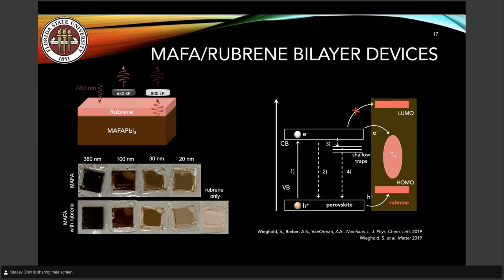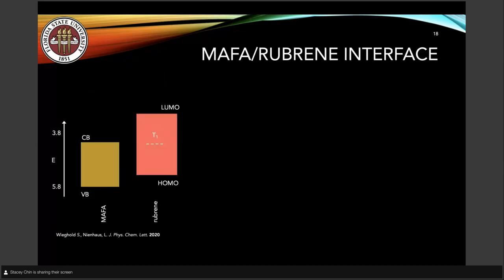And so the idea here is that you excite the perovskite, so you create free carriers, you have a hole in the valence band and electrons in the conduction band, and you do hole transfer and electron transfer to the triplet state of rubrene. Next slide. We spent some time looking at this interface because it seemed to be not quite as trivial as we hoped it would be initially. So what you can see here is essentially the energetics of the valence band and the conduction band and the HOMO and the LUMO of both our perovskite and the rubrene when they're not in contact.